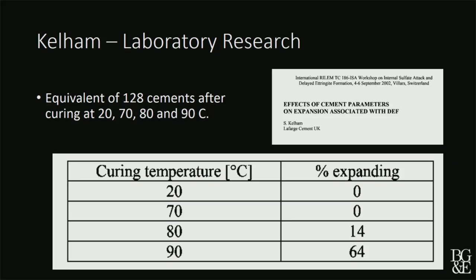And he found that curing them at normal temperatures, nothing expanded. Curing them at 70 degrees, nothing expanded. Curing them at 80 degrees, he had 14% of the cements expanding, which meant most of them didn't expand. But once he got to 90 degrees, over 50% of those cements showed expansion. So this was showing that there is a critical curing temperature, but it's also showing that the cement chemistry may be playing a more important role in the expansion than actually the temperature itself.